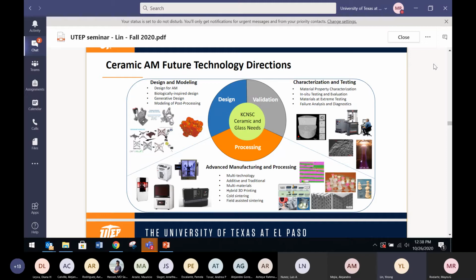But for ceramics, it's not, because you have to bring down the polymer binders, and then you have to solidify ceramics. It's going to shrink, it's going to distort. So it's hard to predict what it looks like, right? Therefore, we try to pioneer in the modeling of post-processing, so you can predict the final geometries. So during design, you can compensate for the distortion and the shrinkage of the dimensions.